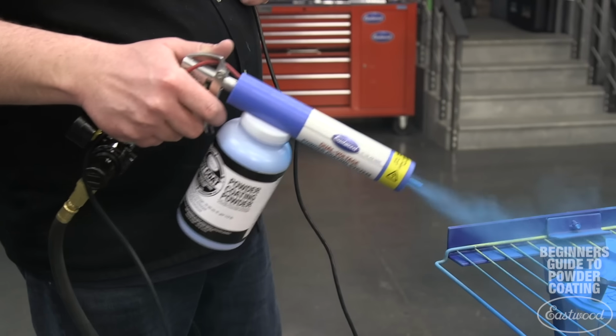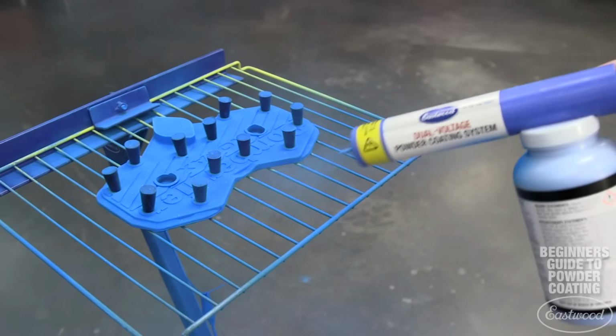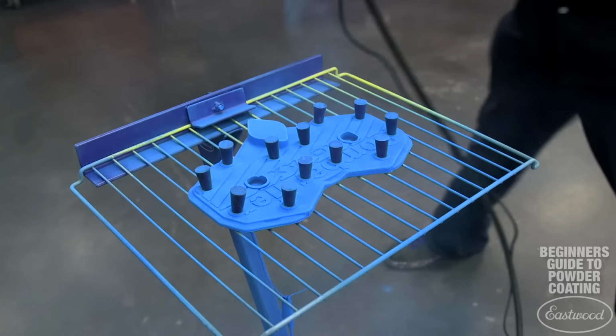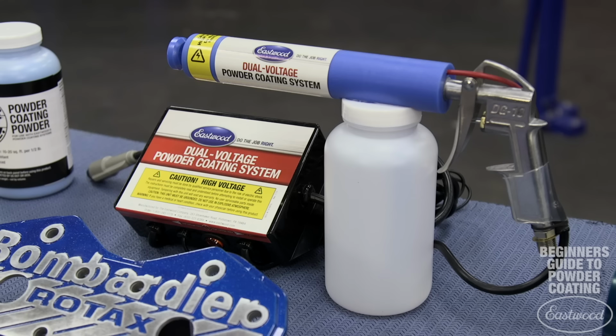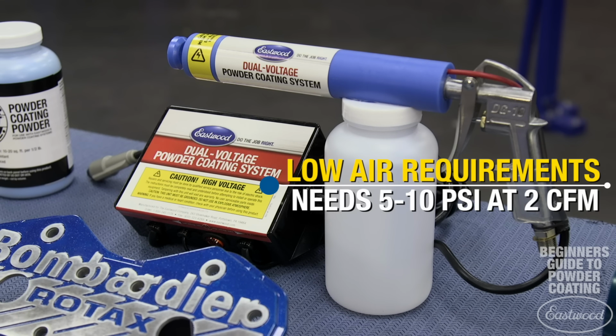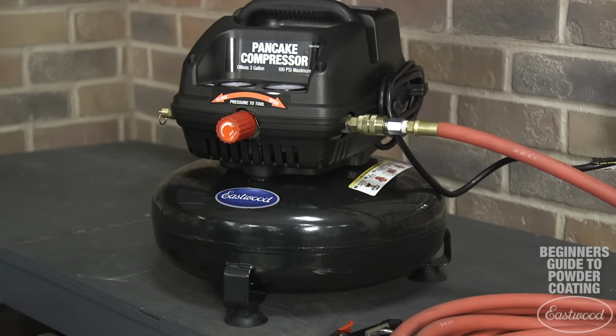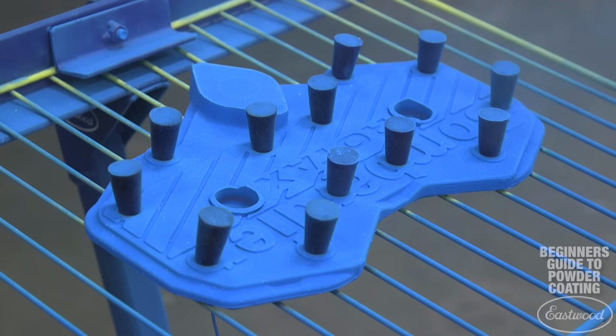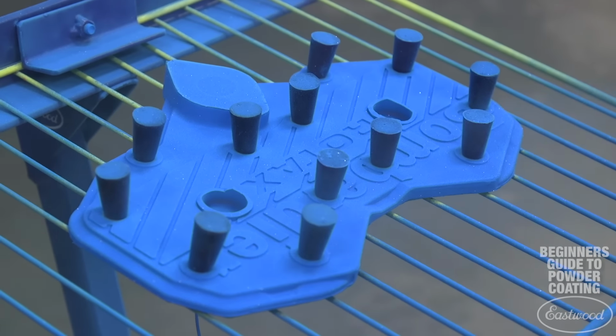Hold the gun about 8 to 16 inches from the part and apply using gentle, steady, sweeping motions while moving around the entire part. The gun we're using only requires 5 to 10 psi at a mere 2 CFM, which is why you can use a small pancake compressor. Apply powder until the part is uniformly covered and you can't see through it.